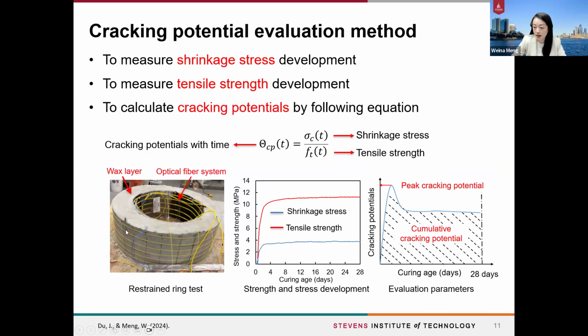We use the ring test for the evaluation, and we installed distributed fiber optic sensors on the ring specimens. This allows us to measure the shrinkage stress development, and at the same time, we also measure the tensile strength development of the concrete materials, and use those two results to calculate the cracking potentials with time. So usually if the tensile strength development always surpasses the shrinkage stress, then we will have concrete with very good cracking resistance.